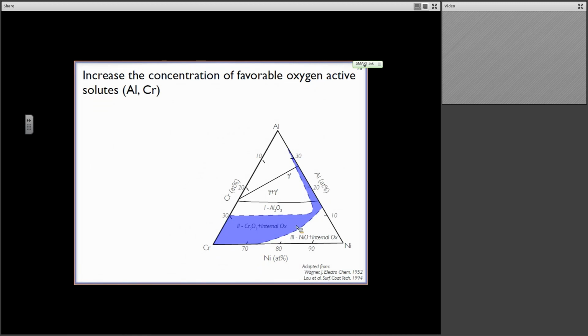If we increase both the aluminum and chromium concentration, depending on how we do that ratio, we would start to form a chromium oxide, and maybe a little bit of internal oxidation as well, because we have that layered or stratified structure of the oxide. But if we dump enough aluminum in, we will get a desirable aluminum oxide scale, with the caveat that we've oxidized it at the right temperature.